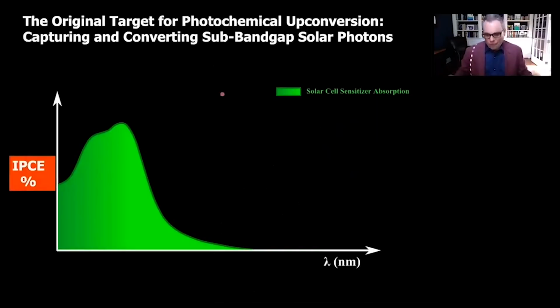And then we immediately recognized something, because my group has had a long history, especially back then, of working on dye-sensitized solar cells. So here's a typical ruthenium complex that would be surface anchored to titanium dioxide. And this is the photo action spectrum, the incident photon to current efficiency in percent. You see the same feature no matter what your sensitizer happens to be. At longer wavelengths, you get roll off. This is equivalent to what happens in semiconductor materials when they cannot absorb the sunlight anymore, so they can't convert those longer wavelengths into photocurrent. And that limits your power conversion efficiency.